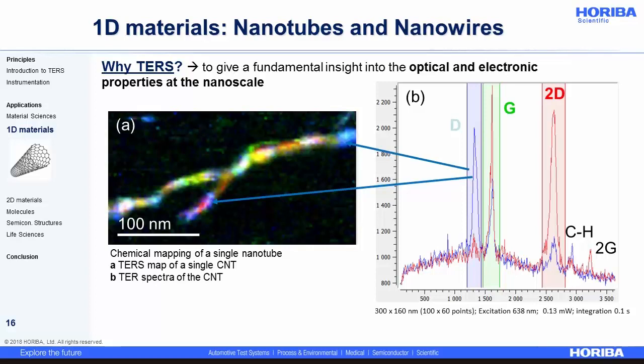So the map shows the distribution of the intensities of three characteristic Raman bands. You have the D band in blue, the G band in green, and the 2D band in red. The representative spectra are shown on the right. So thanks to a fairly high spatial resolution and a reasonable signal-to-noise ratio, we can identify not only the location of the CNTs on the sample, of course, but also see the difference in the internal structure of those two individual carbon nanotubes based on the variation of the intensity of those characteristic Raman peaks.